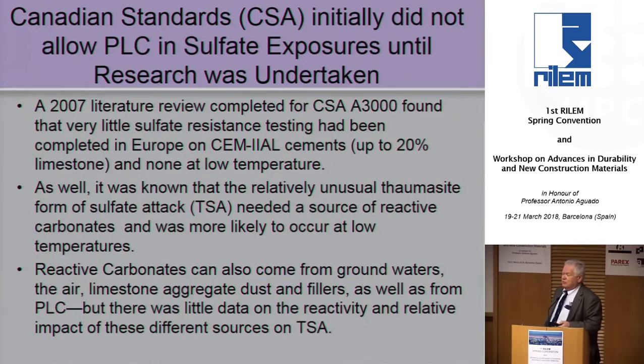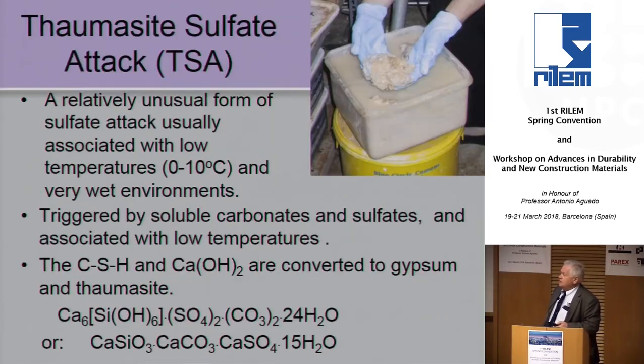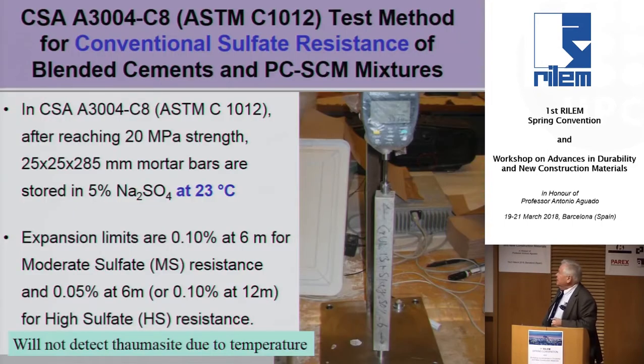And so we wanted to make sure that we did some research before we allowed these cements in sulfate exposures. And we know that when it does happen, it's pretty severe. It's very rare, but when it does happen, that used to be concrete up on the right, it destroys the calcium silicate matrix. So we wanted to make sure we weren't introducing something in the standard that could cause us a problem in these severe environments in a fairly cold climate.